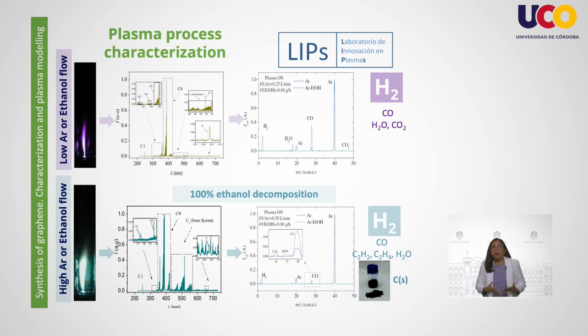However, we observe that when using larger ethanol and argon flows, the process is more effective. Under these conditions, solid material, the graphene actually, is formed in the reactor. Hydrogen is the main byproduct, and more importantly, there is an absence of polyaromatics or greenhouse gases. This is therefore a confirmation that our process is a green process.